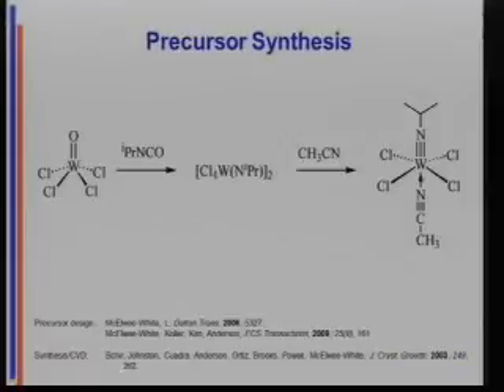If you want to lay down a film that's primarily tungsten nitride, let's start out with a molecule for which a tungsten nitrogen bond is pre-existing, so we know something about stoichiometry, and it's the strongest bond in the molecule. So here's an imido compound. In this particular drawing of it, it's drawn as a triple bond. It is linear, for those of you who are aficionados. That's a very strong trans effect ligand, so my acetonitrile is going to be labile, trans to it.